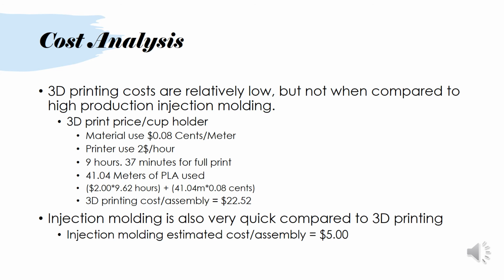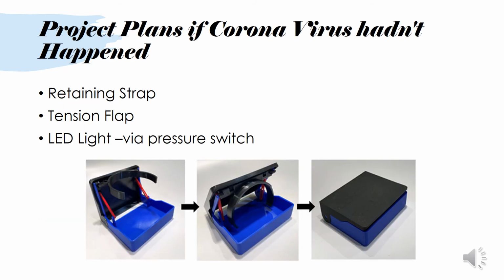We guess that if one were to use injection molding for this process, the price per cup holder would dramatically decrease to a value of around $5 per cup holder versus the $22.52 for the 3D printed cup holder. The 3D printing process is great, but only in terms of printing one-off prototypes. Large scale, the injection molding process would end up yielding better quality parts at almost a fraction of the price.